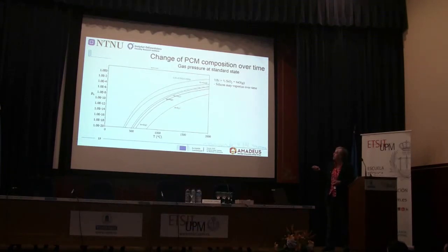So we can see here we are talking about 10 to the minus 10 or 10 to the minus 4 partial pressure of the different gases. If we have silicon and we have some oxygen present, we may produce some SiO gas. At, for example, 1300 degrees C, we will have a bit less than 1% of SiO gas. We see copper has a bit lower, and then iron, nickel, boron, silicon as such are quite low partial pressure.